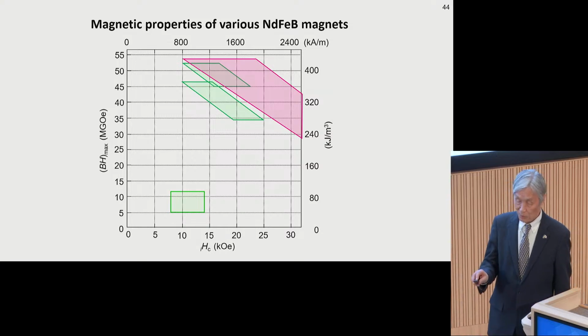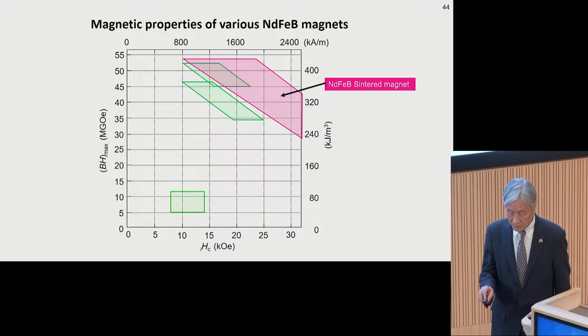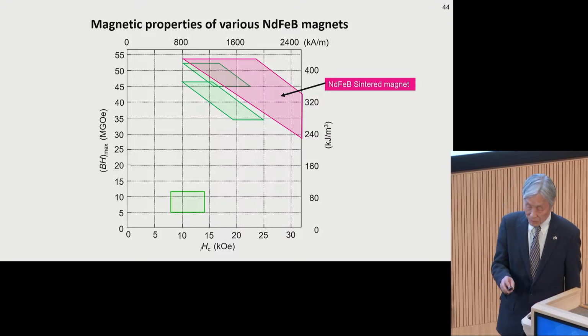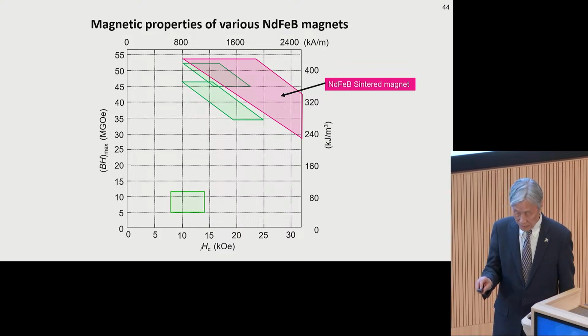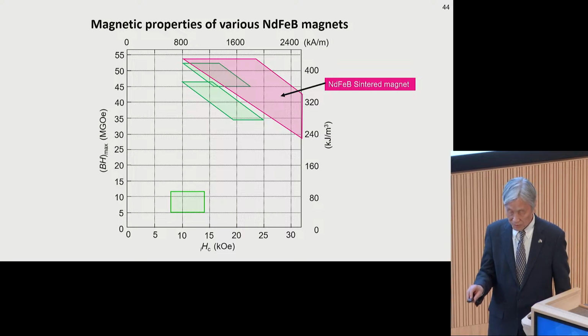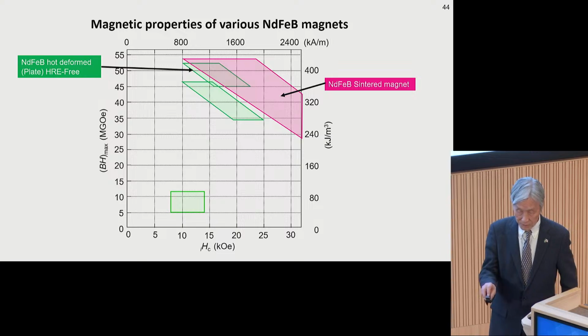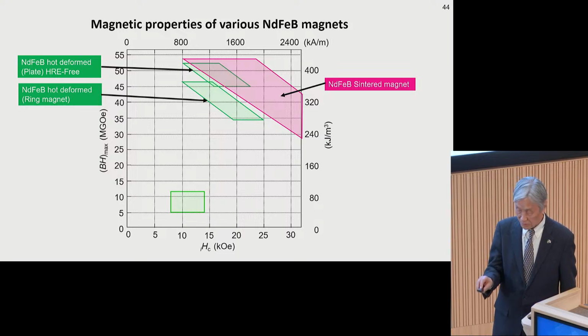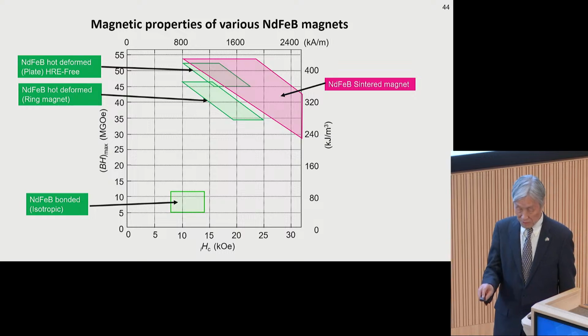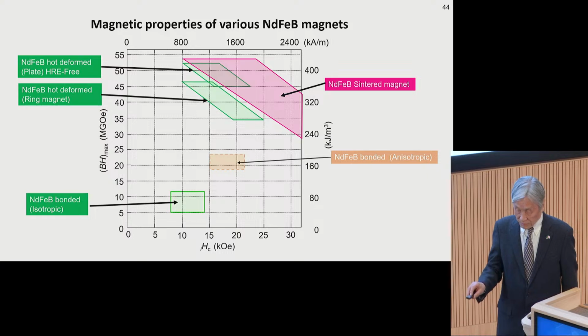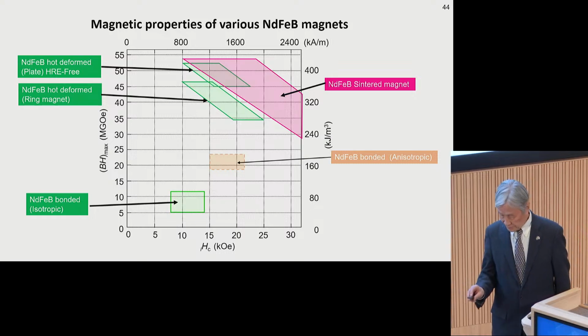Okay, and this shows the magnetic properties of various neodymium iron boron magnets. The BH maximum and the coercivity diagram. As you see, the neodymium iron boron sintered magnet that we developed is in this area, and the neodymium iron boron hot deformed plate-like magnet is in this area, and the ring type hot deformed magnet is in this area, and this is the neodymium iron boron bonded magnet area. The neodymium iron boron bonded anisotropic magnets were produced by another group later.